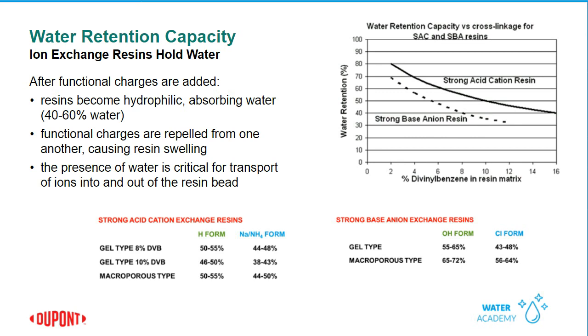You can see in the chart on the right for cation and anion resins that as we increase the divinyl benzene level, we increase the cross-linking of the copolymer, and the resins don't take on as much water. That water retention capacity actually goes down. So it's a measure of the tightness, I guess you can say, of the resin as well. And it's an important parameter for resin analysis of cation resins.